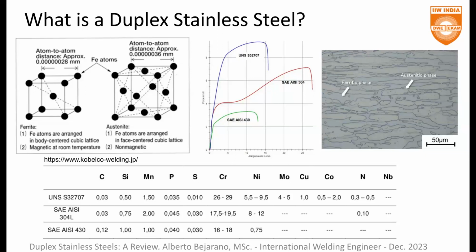Okay, so when we study this alloy under the microscope, we see, in the upper right corner, we have the ferritic phase and the austenitic phase. This micrograph is very well obtained. I mean, as this material has a high corrosion resistance, it is quite difficult to obtain this kind of quality in our micrographs. And this is very important, as you will see in a moment.